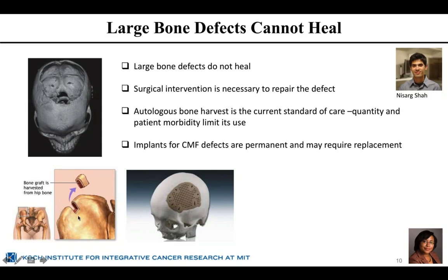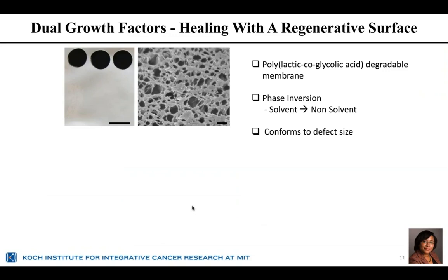This is in place of the traditional approach, which is to harvest bone from another part of the patient's body, such as the hip, grind it up, and then try to regenerate bone from the cells and material generated from that graft, and use something like an artificial implant to help support that. And of course, there are a number of problems with both the sacrificial bone and the introduction of a foreign material into the skull. In our case, we've been using a degradable polylactic glycolic acid membrane, which is generated using